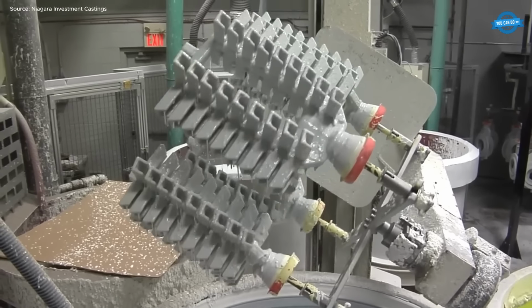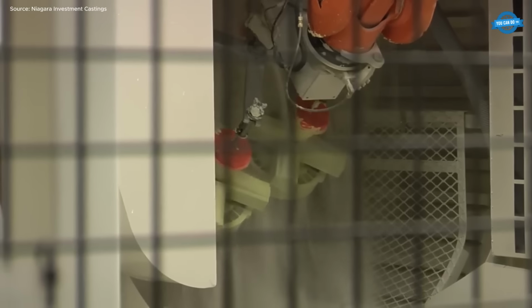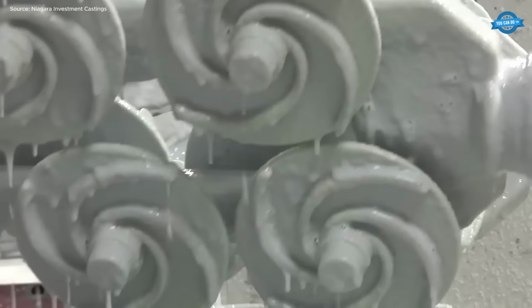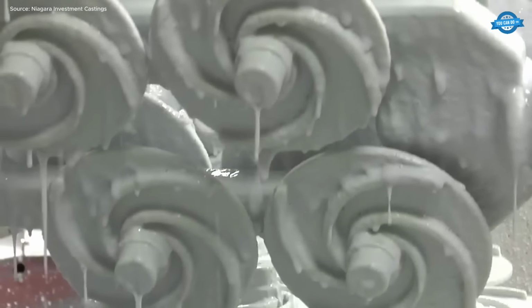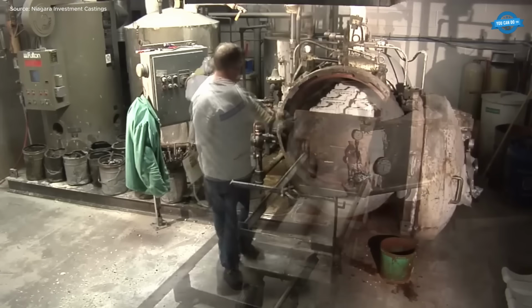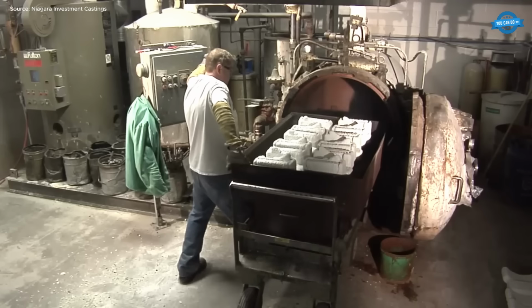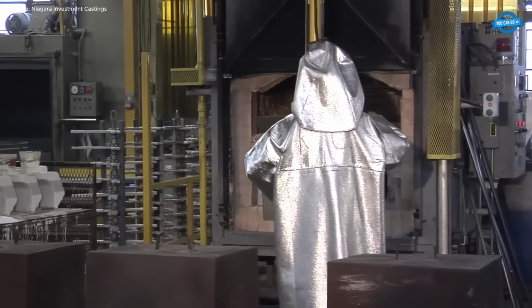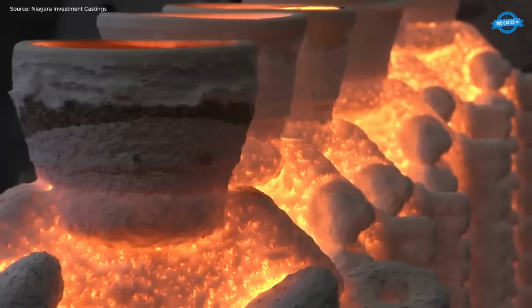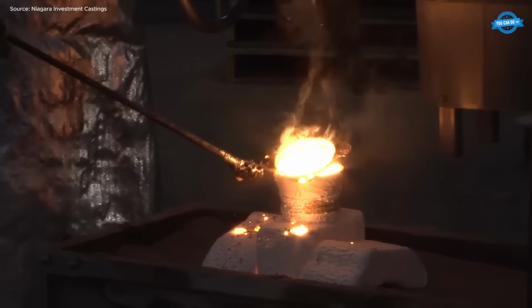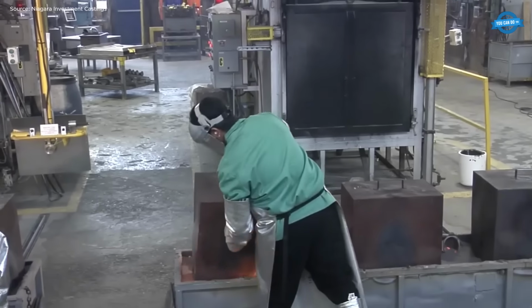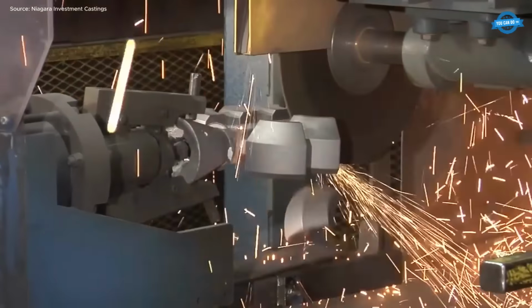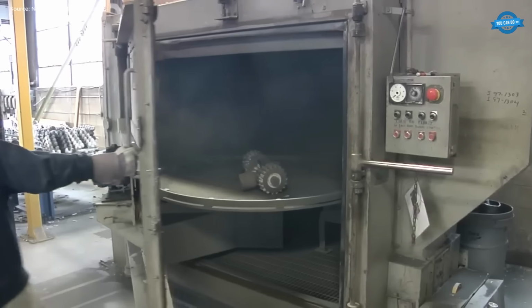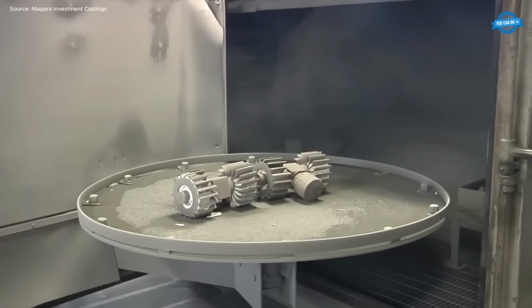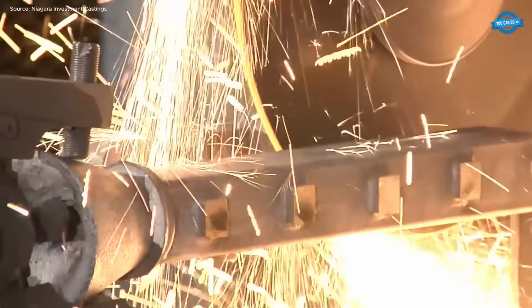This assembly is repeatedly dipped in ceramic slurry and coated with sand, building a robust ceramic shell mold layer by layer. Once the shell is dry, wax is removed through dewaxing, leaving behind a hollow mold ready for casting. The shell is heated to over 1,700 degrees Fahrenheit, 927 degrees Celsius, and then filled with molten metal. The metal adopts the shape of the mold's cavity, capturing fine external and internal details. After cooling, the ceramic shell is broken away, and the castings are cleaned, cut, and finished. Final steps include grinding, NDT testing, machining, heat treatment, or plating to meet customer specifications.